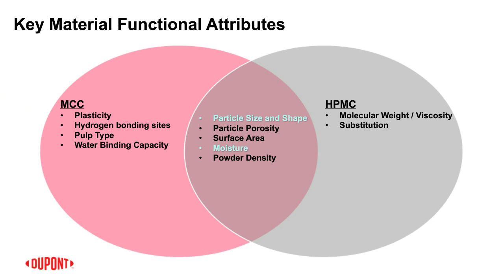And then here on this slide, what we're showing are functional attributes that are common between the two of them, in that overlapping regime, such as particle size, particle shape, porosity, surface area. By the way, this list is not exhaustive. It's really those key ones that we see more commonly in our everyday operations. And then you see the functional attributes that are specific to microcrystalline cellulose, such as plasticity, hydrogen bonding sites, water binding capacity, pulp type, and those that are specific to hydroxypropyl methylcellulose or HPMC, such as molecular weight, which our proxy for that is 2% viscosity, as well as substitution, and we'll speak more to substitution as we move along in the presentation.